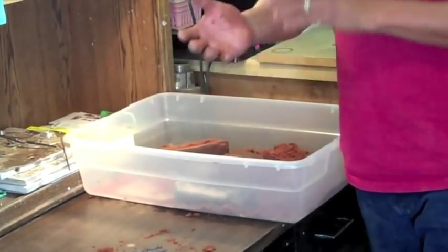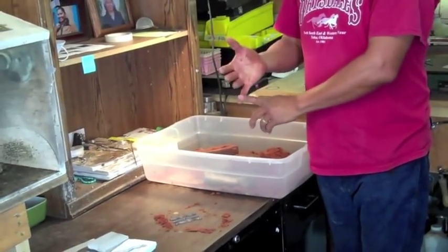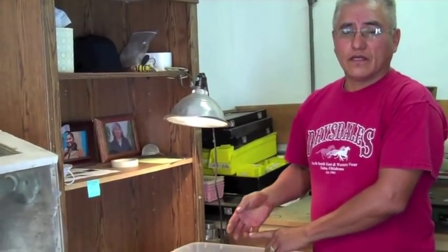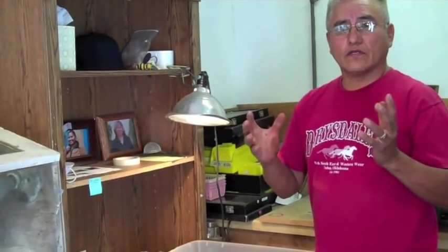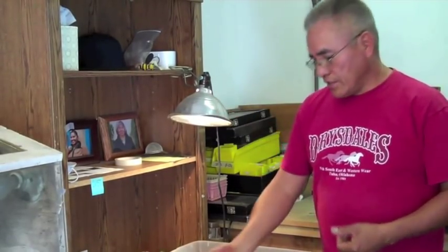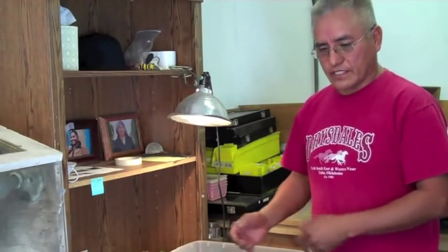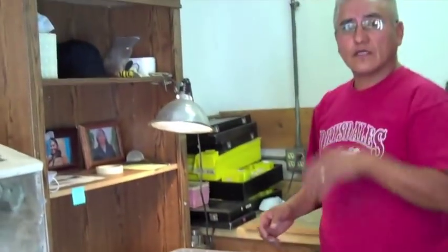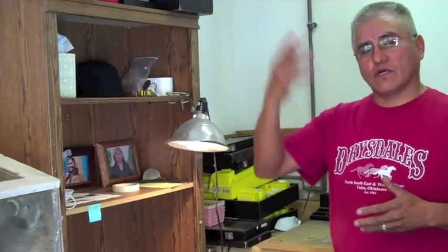It really depends on the ambient temperature in the air. After it rains, don't try to cast, because it's not going to happen. It's got to be in a controlled air space. The air has to be dry inside the room at a certain temperature to get something this complex. Something very easy to cast can come out in colder temperatures. That's why we have little casting rooms. I have a casting room just about this big, and I sealed it off, and I have a vent which ventilates all the gases and all the smoke and everything.